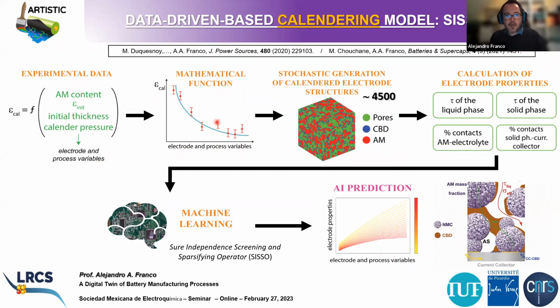And then we have used this correlation function in order to generate a lot of electrode microstructures in 3D. So we have generated a bit more than 4,500 electrodes. This generation of electrodes was performed by using a stochastic approach. That means that we are locating all these active material particles, CBD particles, and pores in a random way in the electrode volume. And then we have characterized these electrode volumes in terms of properties that have some relevance at experimental level. For instance, the tortuosity factor of the pores, which are here assumed to be fully filled with liquid electrolyte.